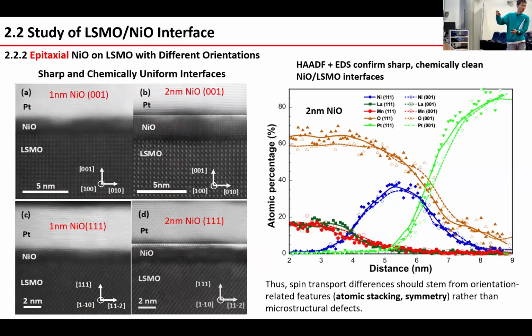Yes, I understand that. But why is it that in image D, I can see a sort of black line in the nickel oxide? And why is it bright underneath? Do you know? This is because of tuning the contrast, because of the atomic number, we have to tune the contrast. So you have changed the contrast, right? But you have changed it for the whole nickel oxide layer, right? Not just for the interface.